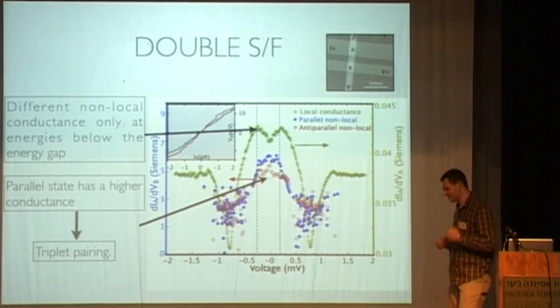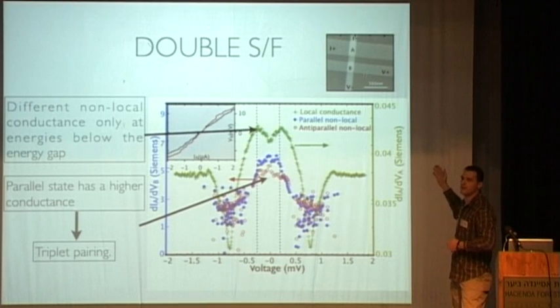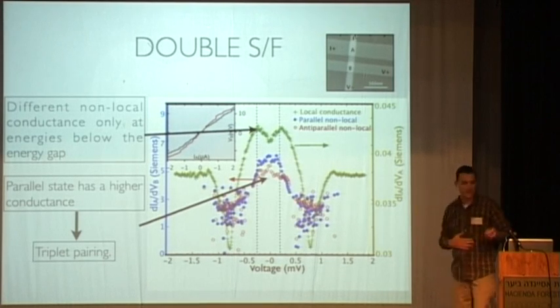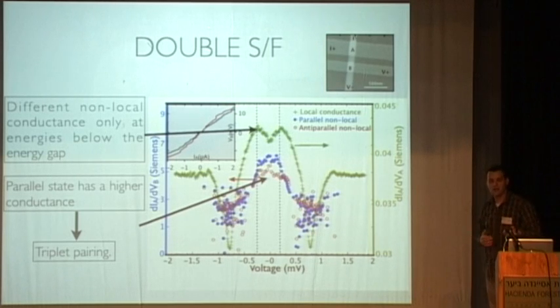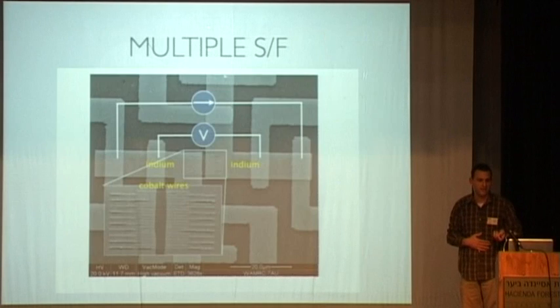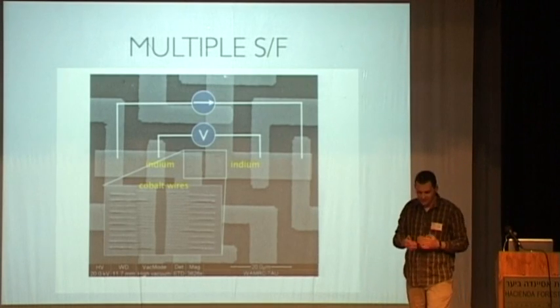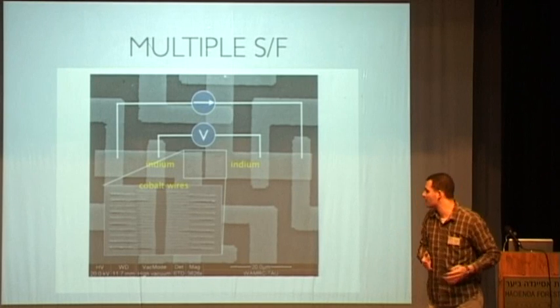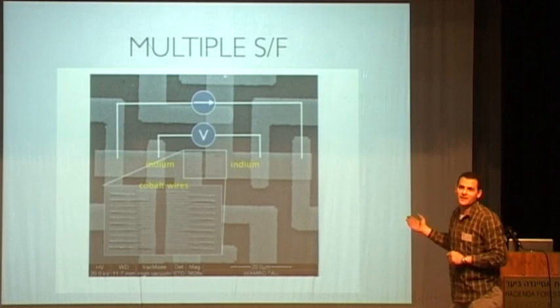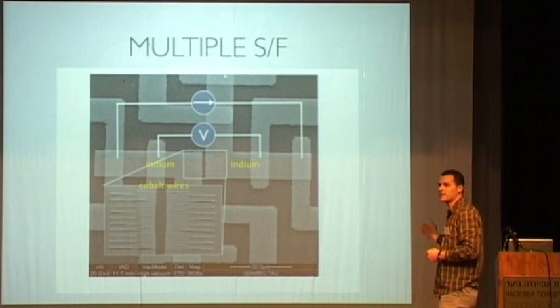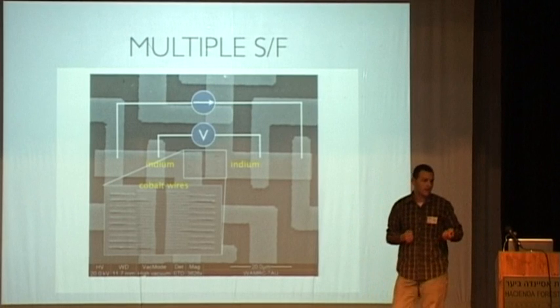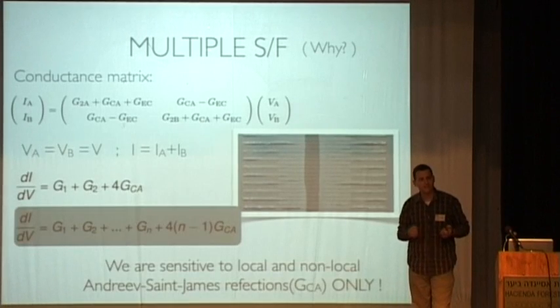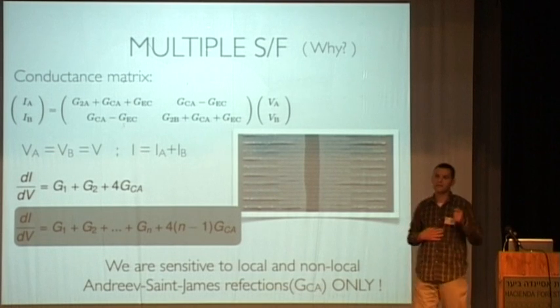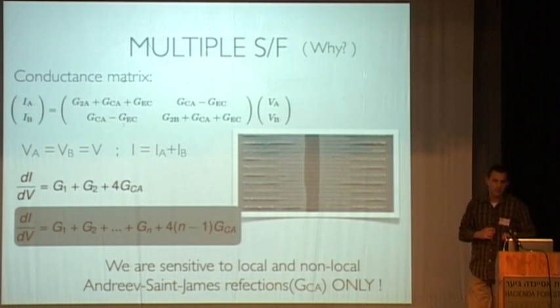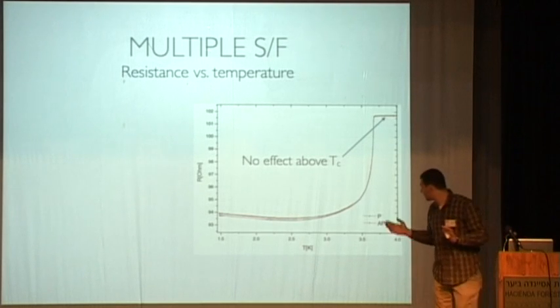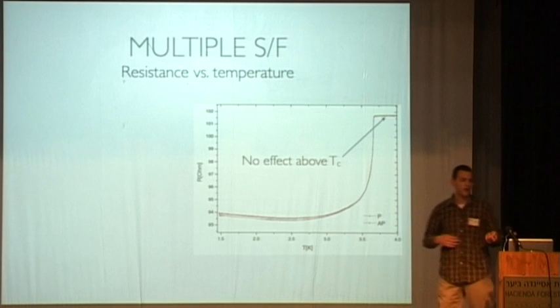Two minutes? Okay, then I'll hurry. We measure the voltage at junction B when we inject the current in junction A. This is a non-local effect which can only happen because the Cooper pair has a finite size. Now, we wanted to simplify things in terms of the analysis, so we came up, or Shai came up with a multiple geometry which looks much, much more complicated, but it turns out that it has an advantage in that we are sensitive in this geometry only to the cross-Andreev term, only to the tool that we want to use.